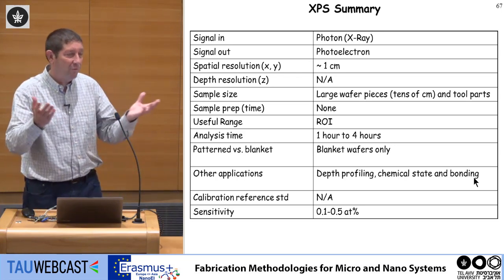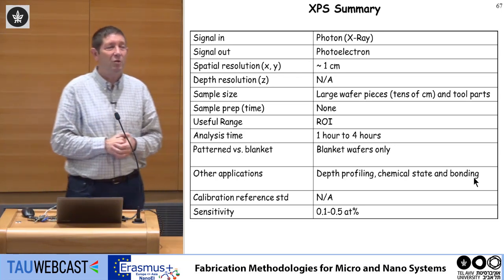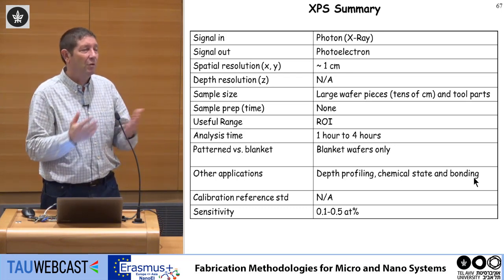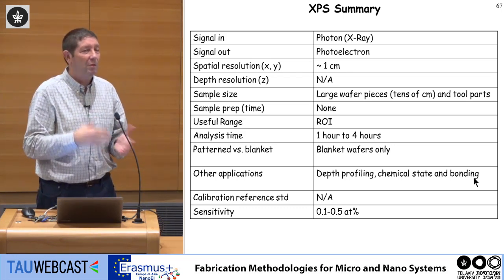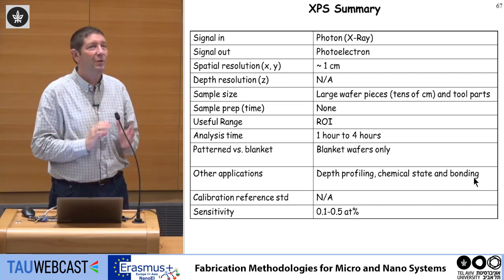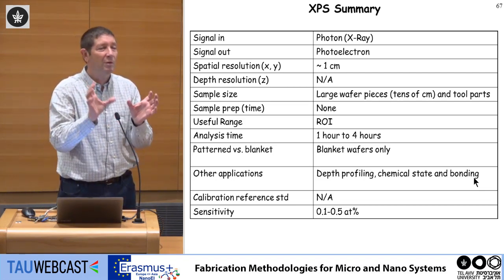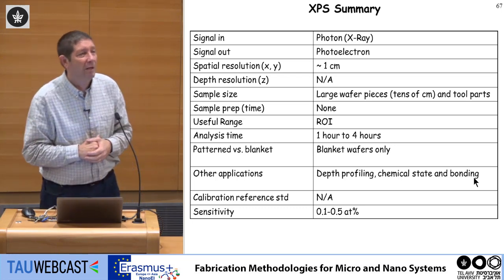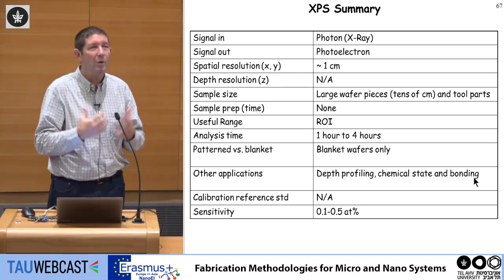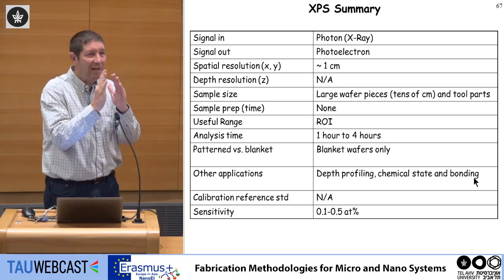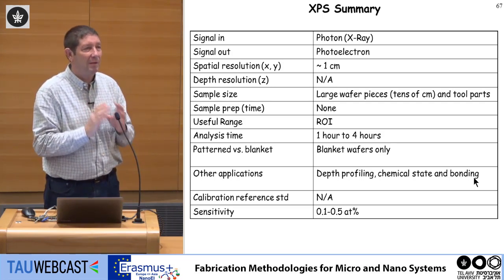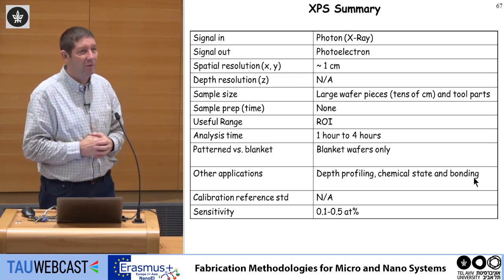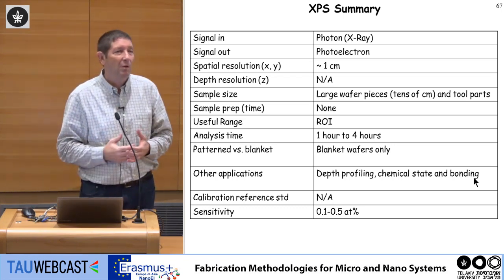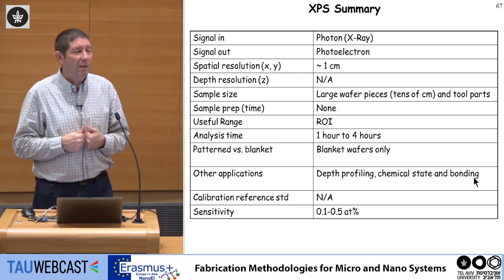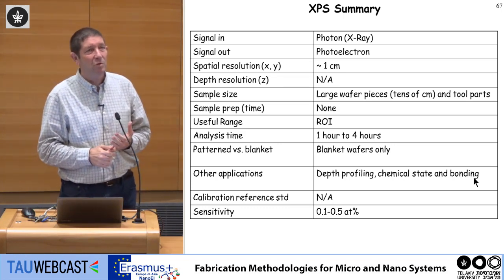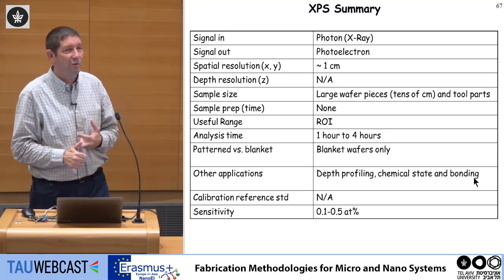For example, we do a lot of study of surfaces of silicon. If you have silicon connected to oxygen or silicon connected to nitrogen, they will have a slightly different energy, because when silicon is connected to oxygen, the bonding is different. So XPS is sensitive not only to what atom I have, but the exact energy can tell me, is this a single silicon atom, or is this silicon bonded to silicon, is this silicon bonded to oxygen, et cetera. So it's a composition analysis, but it also gives me information about the chemistry of the surface.